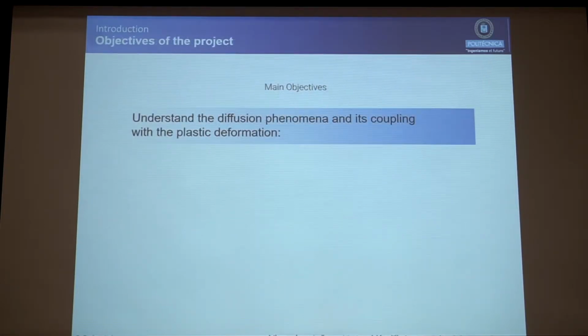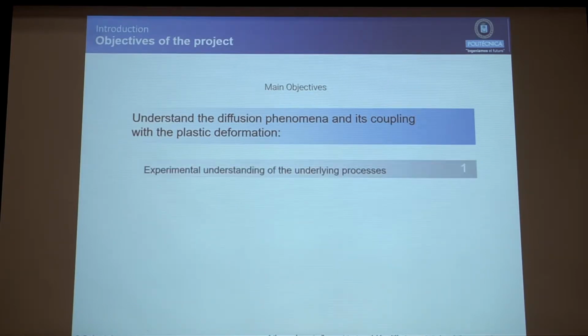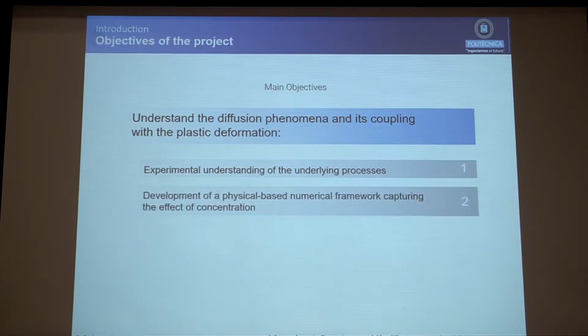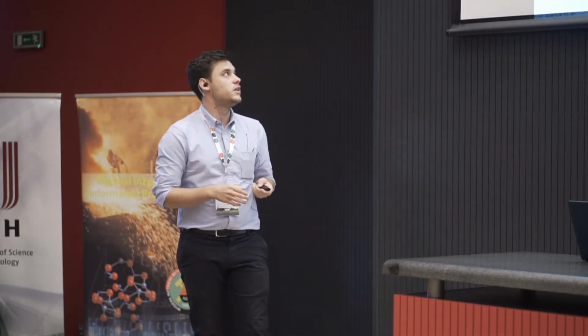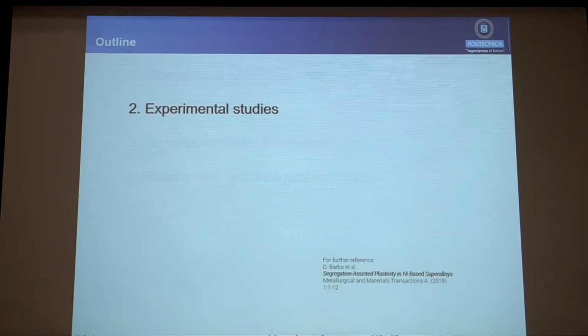So the objective that this project is aiming for is basically to understand this diffusion phenomena and couple this with plastic deformation. In order to do that, we first did some experimental studies to understand the underlying physical processes. Then we developed a physically based continuum model which takes into account the concentration, which is really important because by taking into account the concentration effect, we now can, with these models, develop new grades of chemistries of alloys with superior properties. So I'm going to start with the experimental studies first.